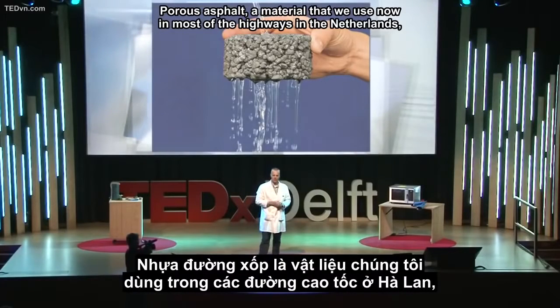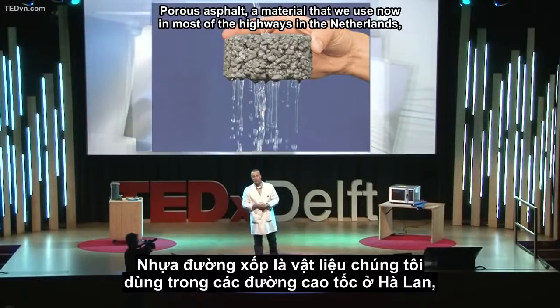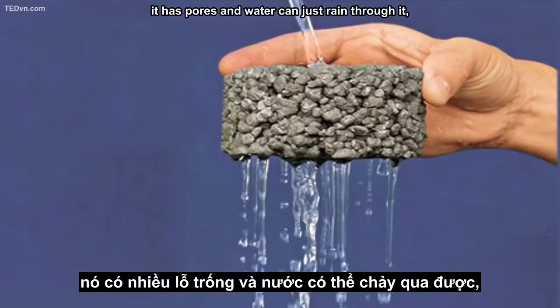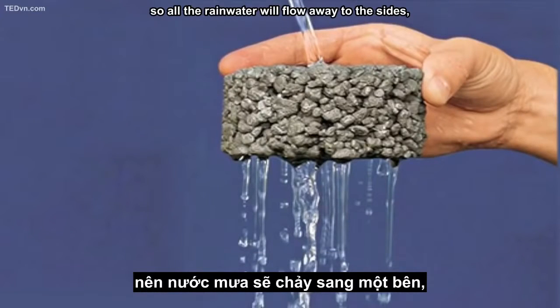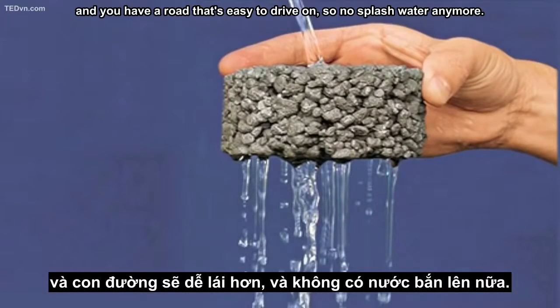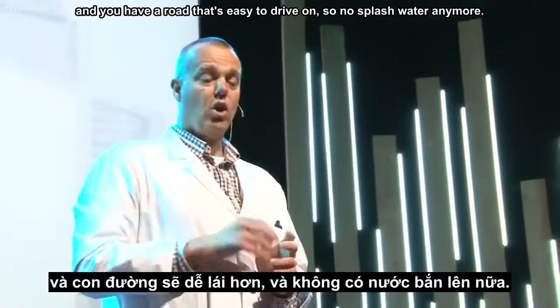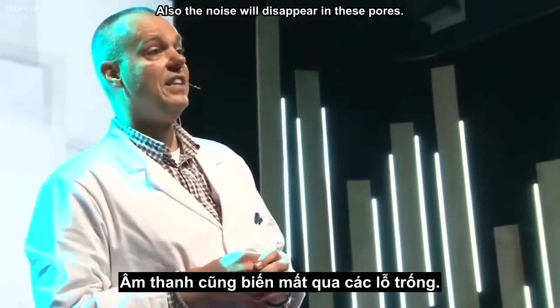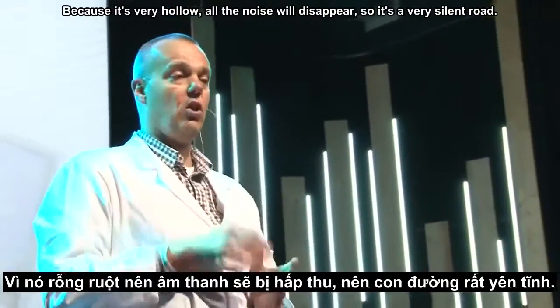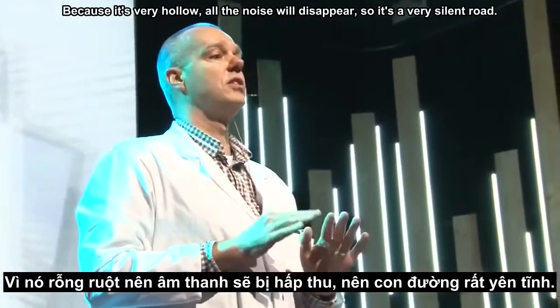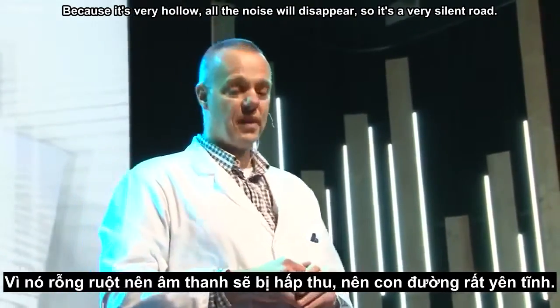Porous asphalt is the material that we use now in most of the highways in the Netherlands. It has pores, and water can just drain through it. So all the rainwater will flow away to the side, and you have a road easy to drive on. So no splash water anymore. Also, the noise will disappear in these pores. Because it's very hollow, all the noise will disappear, so it's a very silent road.